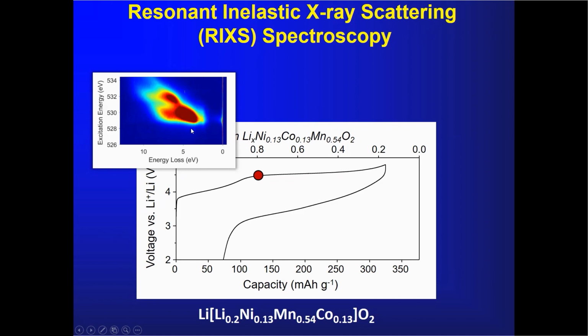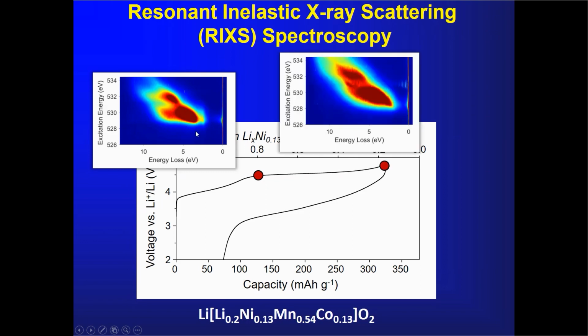I think I'll show you an expanded region at one excitation energy, which I think is more informative. But they are useful, and they show you where there is mapping out emission, as you see. Now you see a RIXS map collected at the end of oxidizing our oxide ions, end of charging here. And those with good eyesight might spot that there are some features in this region. But I'm going to make it easier for you.